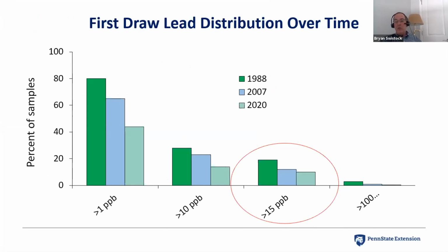So what we have seen as a result of these regulations is decreasing lead occurrence over time for the most part. This is private water system data, so mostly water wells, but also springs in Pennsylvania. The first study in 1988, if you look at the far left there, the percent of the samples in that study that were detectable above 1 part per billion of lead was 80%. So almost 8 out of 10 homes that we did had detectable levels of lead. It dropped down to just over 60% in 2007. And then last year, the most recent data, we have about 40% that have detectable levels of lead.